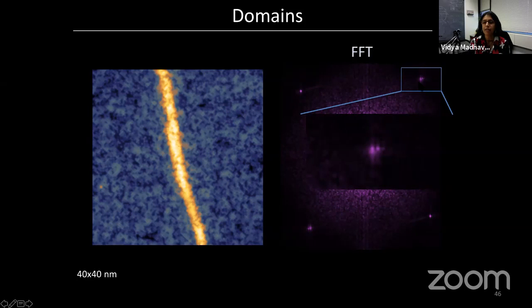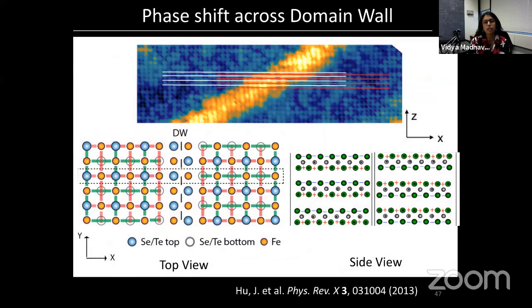This peak has split into two, and that's because in these two regions, the crystal structure is shifted. The splitting of the peak just tells you that you have a shift in the crystal structure, but to see that it's a half unit cell shift, we can do a Fourier analysis and look at the phase, and I'm not going to show you that today. You can do something crude and track the atoms with your eye. So the white line is the line of atoms on the left-hand side. The red line is the line of atoms on the right-hand side. And you can see that the white lines and the red lines are shifted by half units.